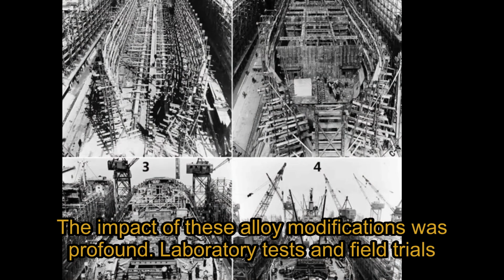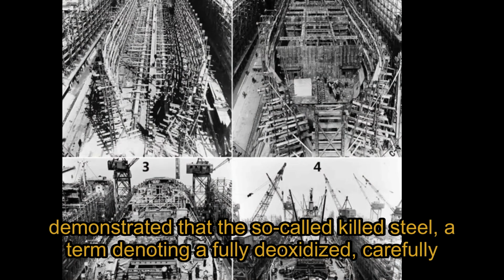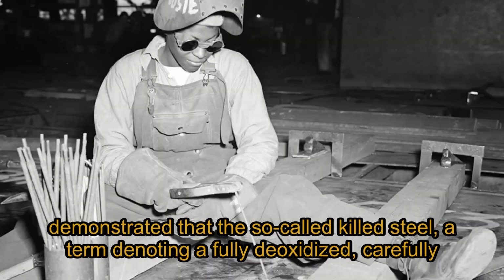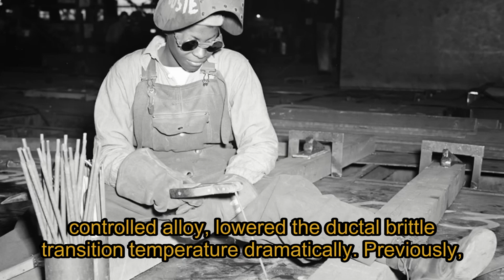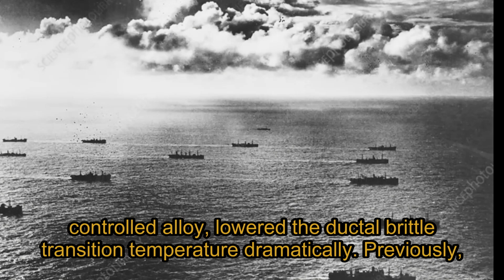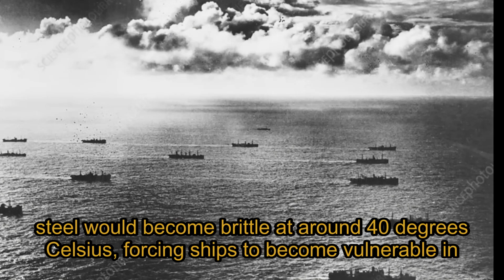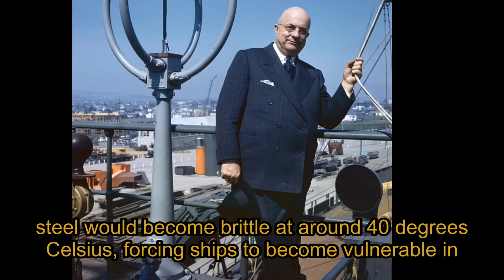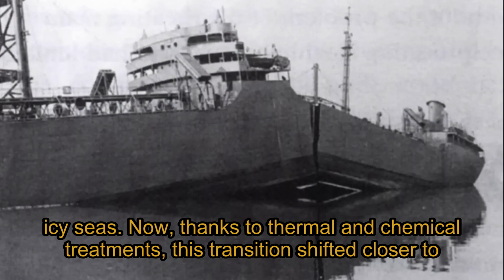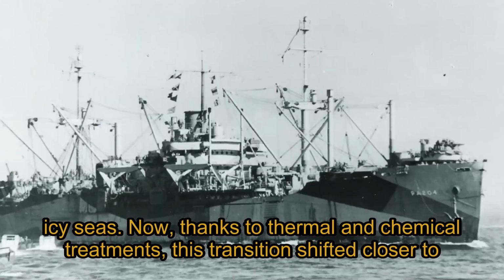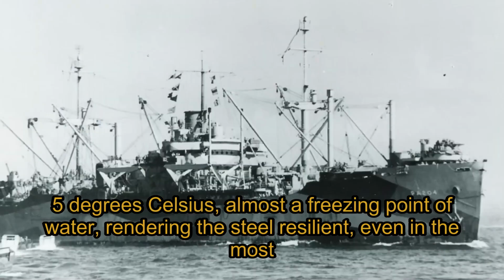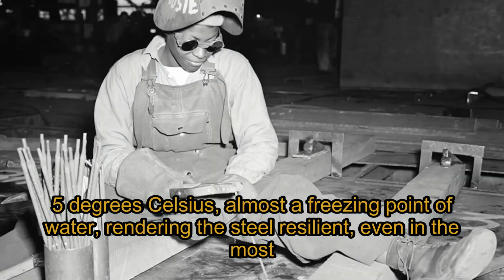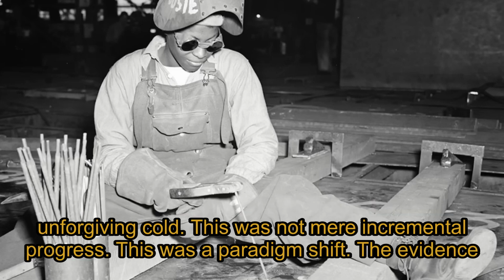Laboratory tests and field trials demonstrated that the so-called killed steel, a term denoting a fully deoxidized, carefully controlled alloy, lowered the ductile brittle transition temperature dramatically. Previously, steel would become brittle at around 40 degrees Celsius, forcing ships to become vulnerable in icy seas. Now, thanks to thermal and chemical treatments, this transition shifted closer to 5 degrees Celsius, almost the freezing point of water, rendering the steel resilient even in the most unforgiving cold.